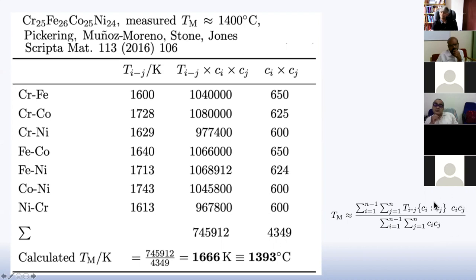I don't have a theoretical justification for doing this. But what we are doing effectively is empirically using data from binary alloys to work out a melting temperature for any number of components in your sample.